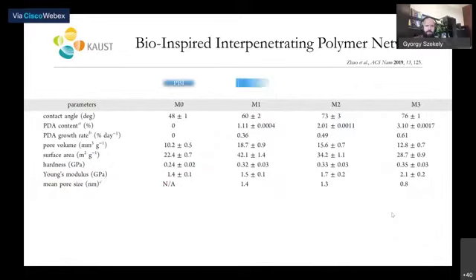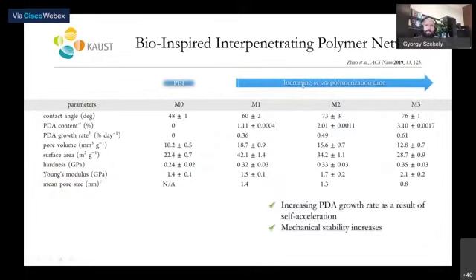Then we looked at the characteristics of these membranes, and you can see that as you increase the in situ polymerization time of the polydopamine, you get different characteristics of the membrane. We looked at the contact angle, we investigated the PDA content, the growth rate, pore volume, surface area, and so on. What you can see here is that when you move from membrane 1 to membrane 2, then membrane 3, basically you're increasing the polymerization time going from left to right. Then you have a self-acceleration of the polymerization of your PDA, and you increase the mechanical stability of your membrane.